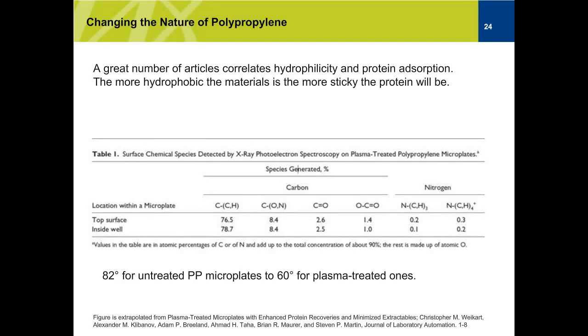So what we did is we employed advanced plasma treatment on our polypropylene to change its nature. As we know, polypropylene is hydrophobic. There are a lot of scientific articles out there that relate hydrophobicity with protein binding, and the more hydrophobic the surface is, the more it will bind to proteins. We know polypropylene is hydrophobic, so the challenge for us was how to change that outer surface and make it hydrophilic. We went with the plasma technology. We added different functional groups that are covalently bonded to the polypropylene surface, and we made our surface a little bit more hydrophilic.